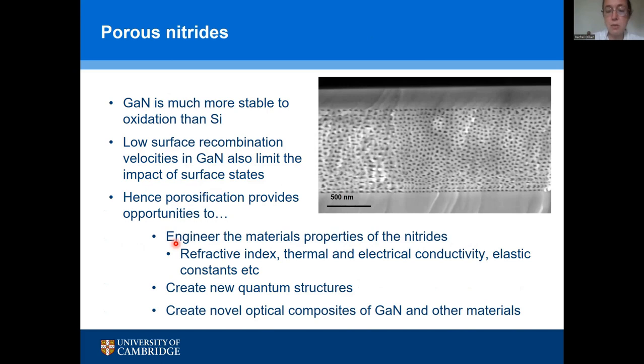We're looking at a material which also has very low surface recombination velocities, which means that it's less easily affected by surface states, less vulnerable to surface states. And since creating porosity, this is some porous gallium nitride, creates lots of surface, being immune to surface states is a really good thing.